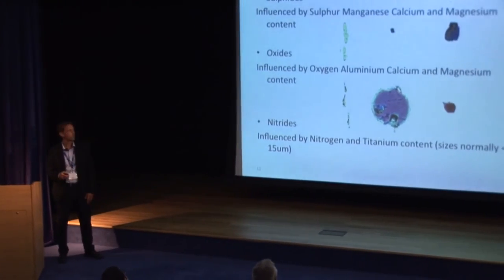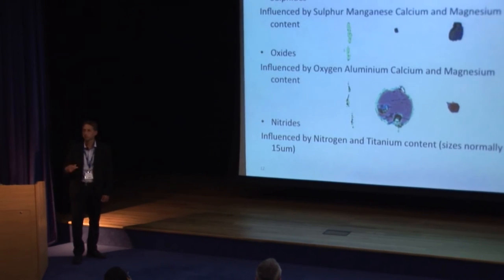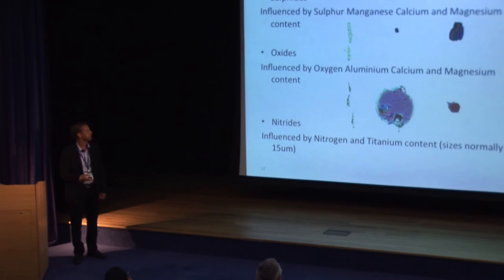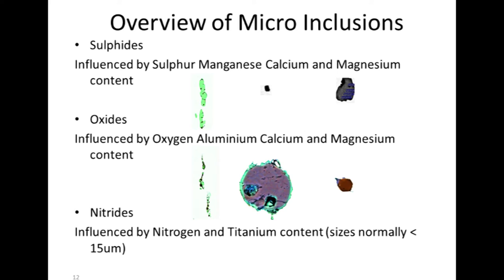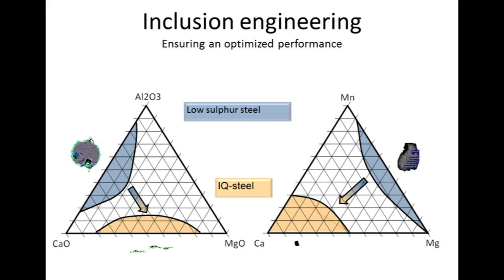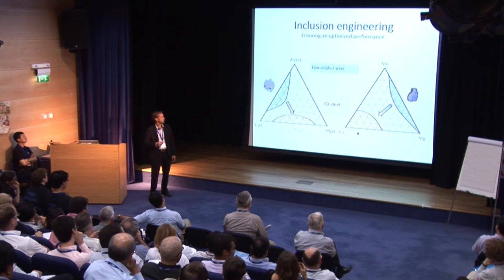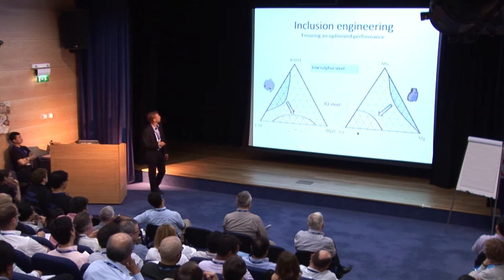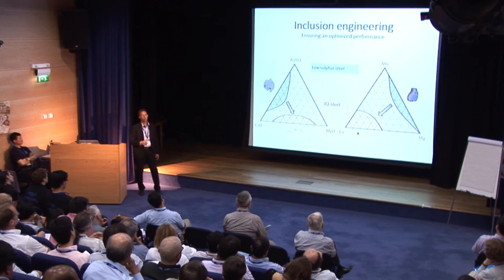So today we have a possibility to choose, by controlling the process in different ways, different inclusion sizes, shapes or morphology and compositions. It's sometimes represented that we can choose how to set the inclusions in order to be as harmless as ever possible. Going to just low sulfur steel, just lowering the sulfur content, might not be sufficient, because then we know we will end up with quite big calcium aluminates. We need to do something else, and then we can start to make inclusion quality steel, as we call it, which changes the compositions into more deformable ones.